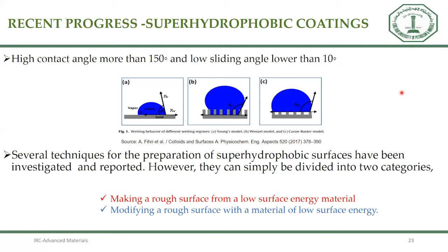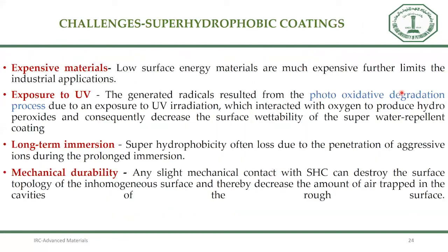Still, we are having some issues in developing the superhydrophobic surface on epoxy coatings, because usually low surface energy materials are expensive, and whenever we expose them to UV, because of photo oxidative degradation, they can lose this property. Also, with long-term exposure, it loses its superhydrophobicity.